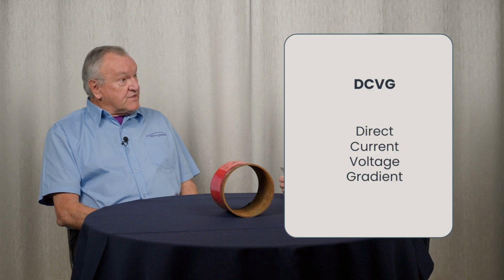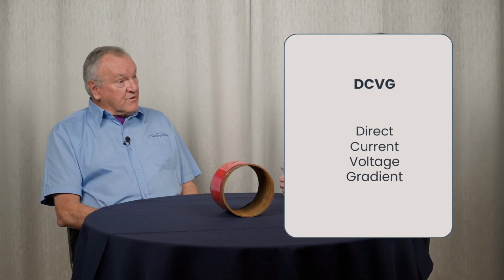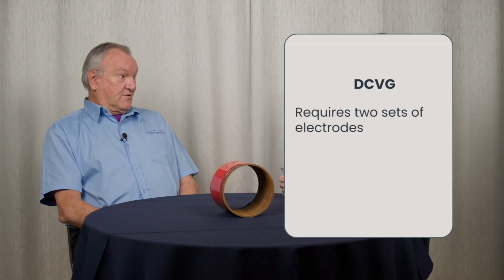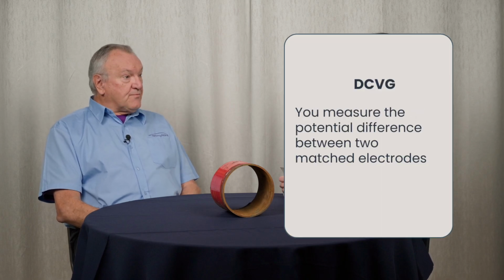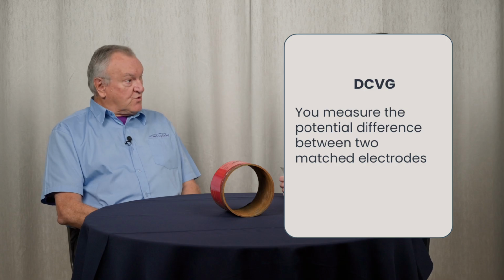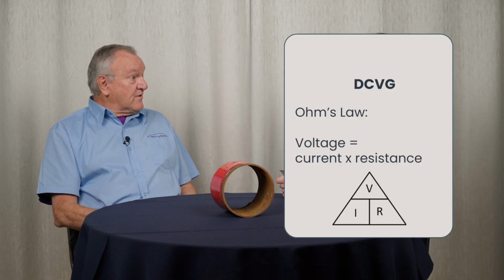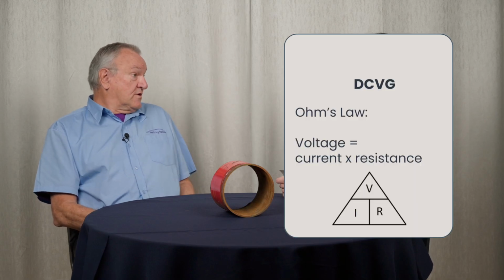And then the DCVG survey, DCVG standing for direct current voltage gradient, it requires two sets of electrodes, and you measure the potential difference between two matched electrodes. And as you well know, if you've got a resistance and a current flowing, it develops a voltage, a potential, Ohm's law. Right. And so we measure that potential gradient. And that tells us information about the condition of the pipeline wrapping.